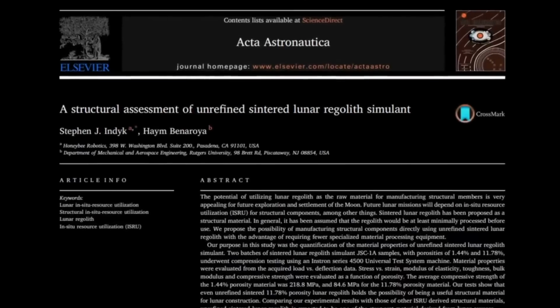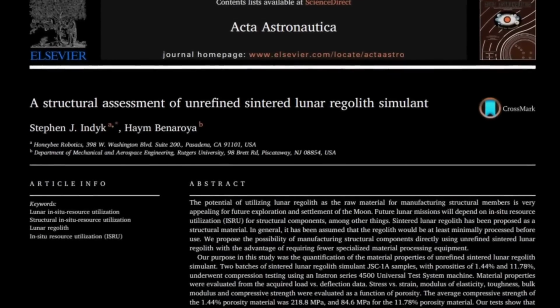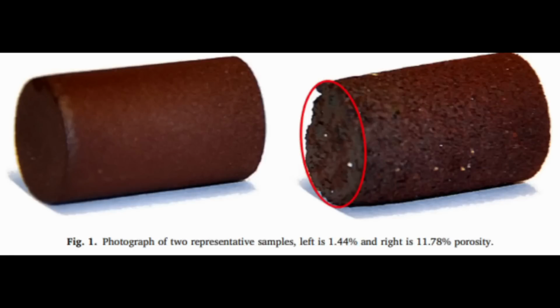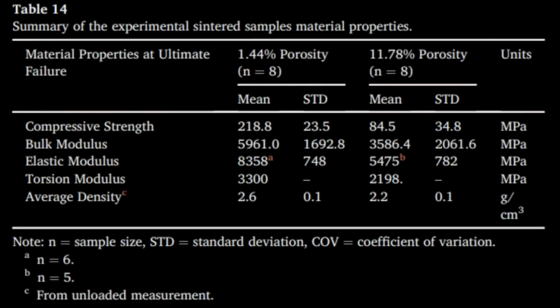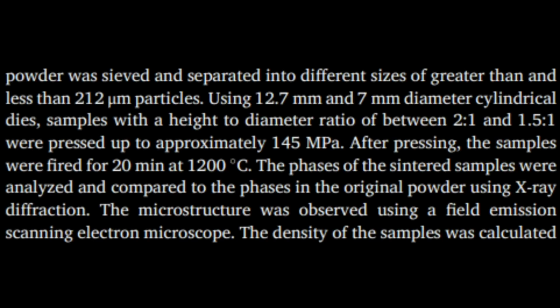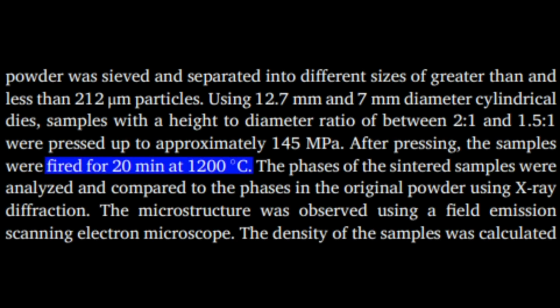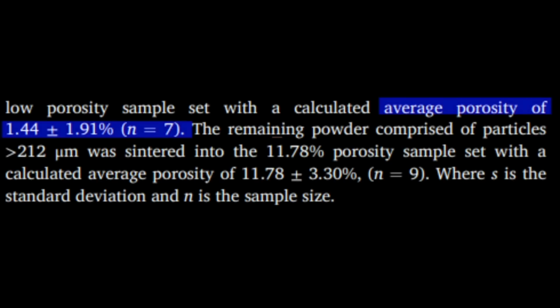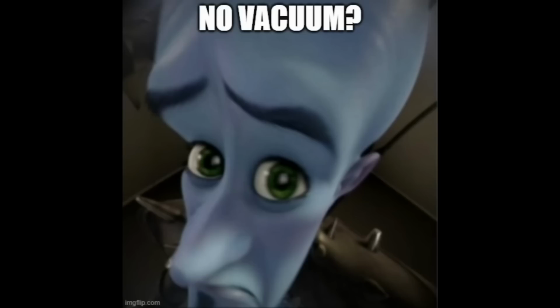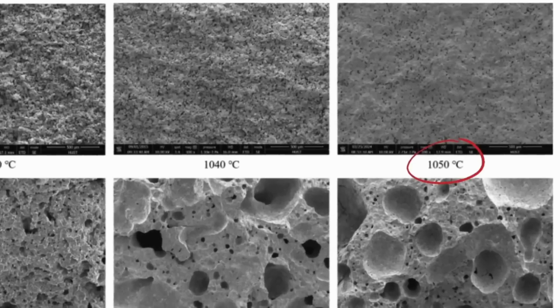which will release gas and create pores, which will make the sinter weaker. For example, this paper from 2017 measured sintered regolith's properties and found the regolith to have an elasticity modulus of only about 8 gigapascals and a much worse tensile and compressive strength as well. But the regolith sintered in the study was done at a much higher 1200 degrees Celsius temperature, which led to the sample having 1.4% porosity, and it wasn't sintered in a vacuum like the samples in the more recent study. We don't know the porosity percentage of our 1050 degree sample, but by just looking at the SEM pictures, we can tell it's very low.